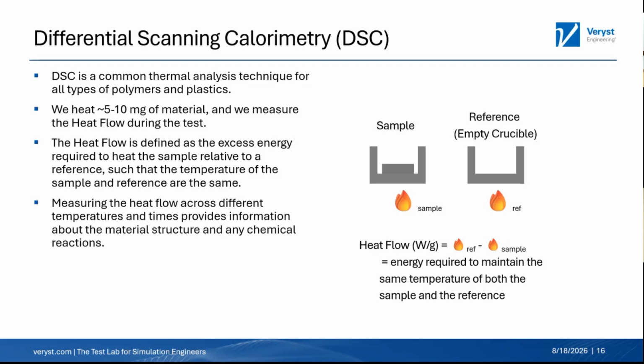It's calorimetry. What we're doing is we have essentially two crucibles, one that has your sample in it and one that's just empty. And the DSC, the tool itself, is programmed to heat both of these crucibles at the exact same rate. So typical rates are between 1 and 20 degrees Celsius per minute. Just as a baseline to compare to. There are other methods to use extremely high heating and cooling rates, but that's the standard for these. And one thing to note is that we're usually using only about 5 to 10 milligrams of sample. So one of the real advantages of DSC is that you do not need very much material.